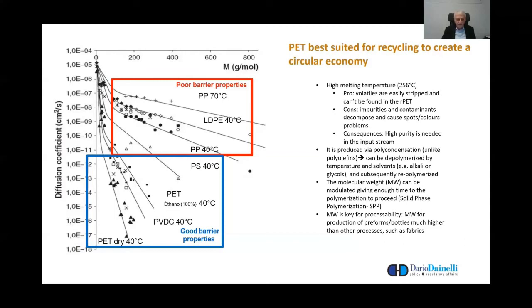The molecular weight is very important for processability. In fact, it is well known that for the PET bottles, the PET quality requires a higher molecular weight than the grades used in other applications such as fabrics or textiles. The diffusion coefficient, which corresponds to the rate at which a certain molecule travels in the polymer matrix, can provide an explanation of the PET behavior. PET has a much lower diffusion coefficient compared to, for example, polyolefins. That means that the contamination takes place at a lower rate and will remain more superficial compared to other polymers. And this makes the decontamination easier. Especially this is true in dry condition, where the plasticization effects caused by moisture are reduced.